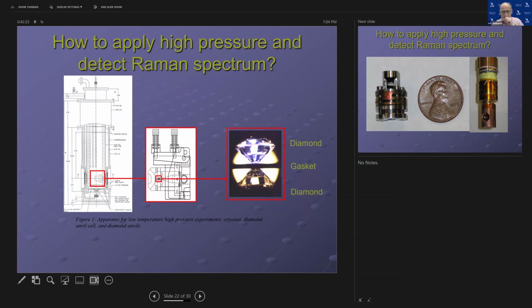In other words, the small volume you can barely see on the slide is squeezed from all sides. That's why it's called hydrostatic. So then you have a system of nuts and bolts that transfer force to the diamond anvil cell. So basically, you squeeze those two diamonds. To create high pressure, you need to have some force and very small area. And since this hole is very small, you have quite small area. So with a reasonable force, you can create very high pressure.